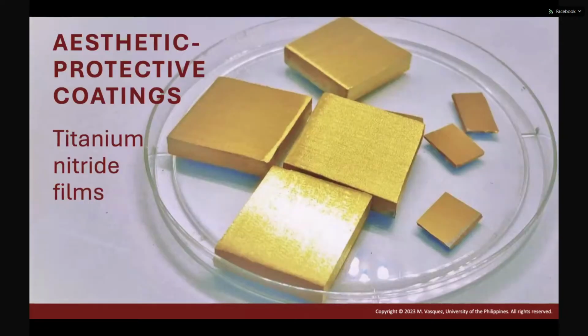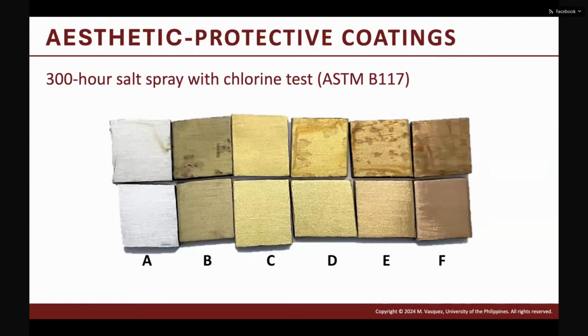So in our lab, we've been developing aesthetic and protective coatings. What we want to do is to try to mimic or produce gold coated tools or surfaces. If you're familiar with titanium nitride, it is actually gold in color. But still, you need to tune certain process parameters such that the color is similar to gold. And we were able to test this. It's really close to the natural gold color. Aside from that, because it's titanium nitride, it also has good anti-corrosion properties, at least with this test.